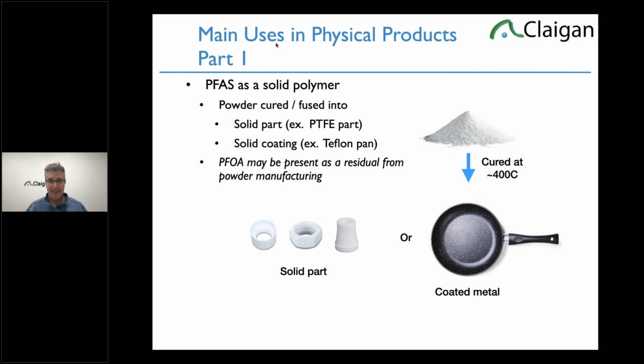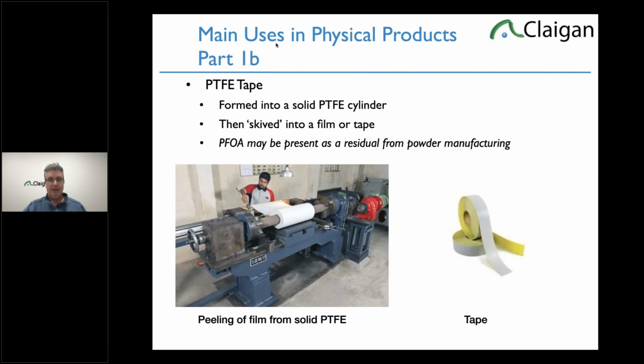However, it is banned in the EU. So this Teflon part, if you don't know where all your PTFE parts are, you're very vulnerable in the EU because you can easily have PFOA. You don't have to. Having PTFE does not mean you have PFOA. It means you can. It just depends what processing it is. It's not part of PTFE. PTFE does not degrade into PFOA. It's not a degradation product. It's literally a manufacturing aid that could be added and doesn't have to be. There are other options. It's better at it, but it doesn't have to be. So that's solid PTFE or metal-coated PTFE.